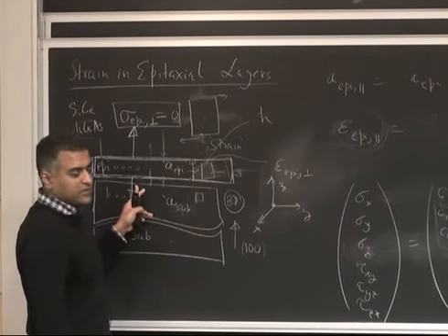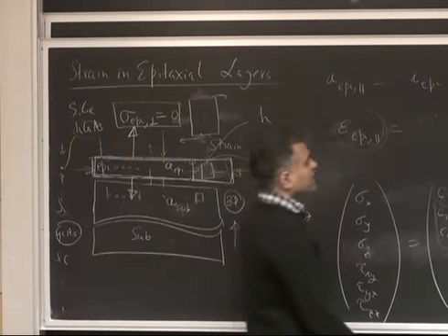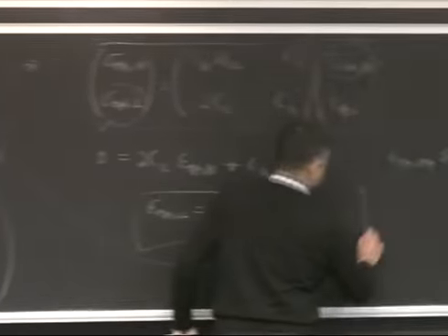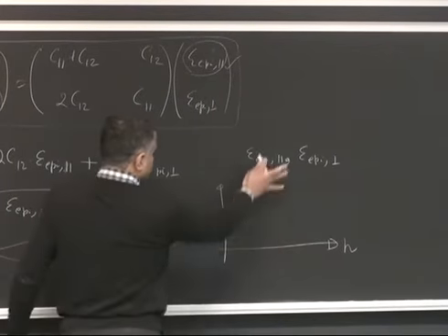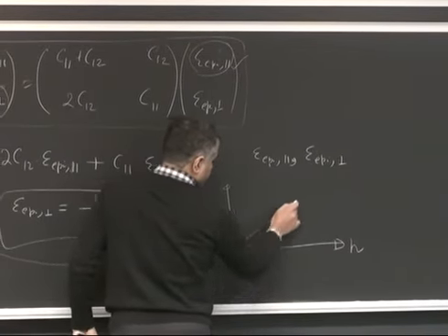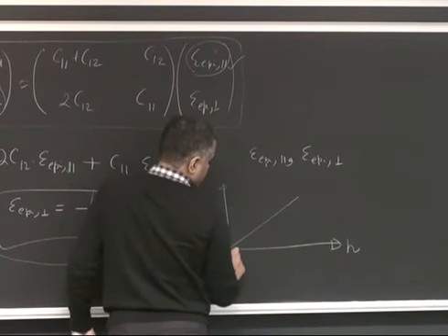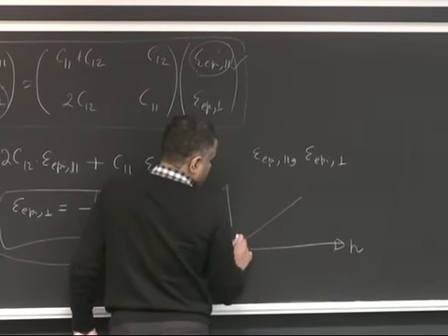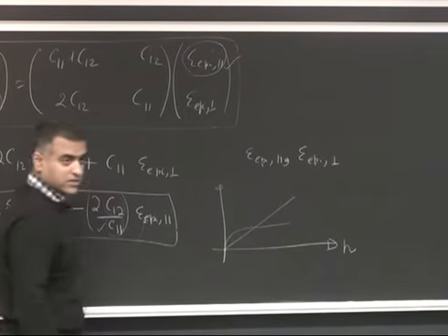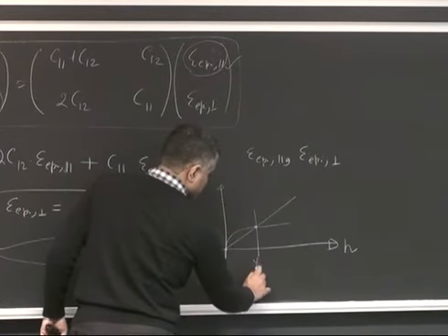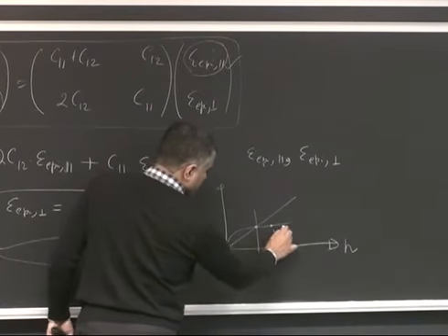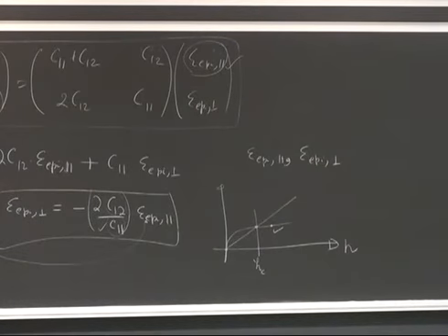So at some point of energy, I think maybe I had sketched something in a hurry last time, but essentially what we're going to do now is find that the energy cost of remaining coherent because of strain is going to grow linearly with h, whereas that of forming dislocations will be something like that, logarithmic growth. And therefore, beyond a certain thickness, which we'll call the critical thickness, it is more energetically favorable to form defects rather than keeping it coherent, keeping your strain.